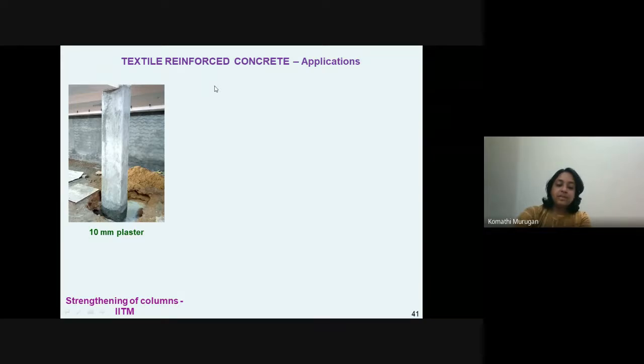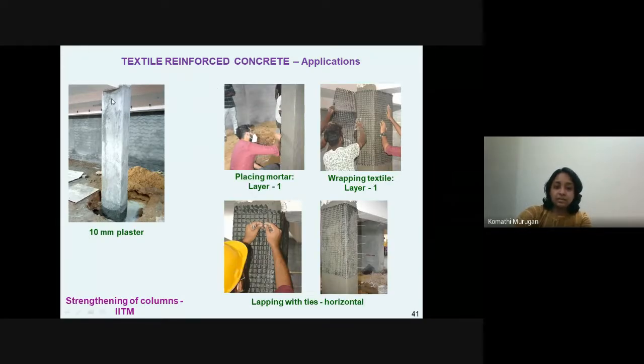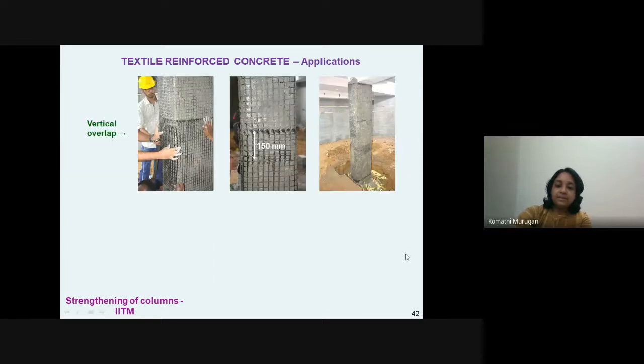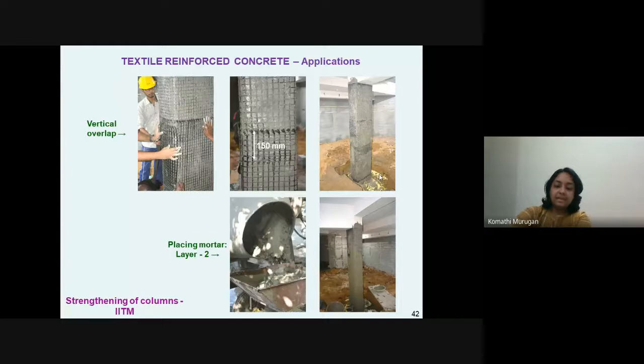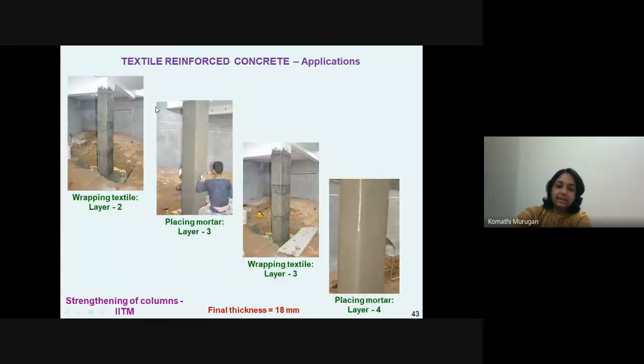What we did is we gave a plaster on the hacked surface of the columns, and we placed the mortar, and wrapped the first layer of textile, giving the vertical as well as the horizontal laps, because over the height of the column we had to give three parts of textile, as these textiles were available only at certain widths, so we had to give certain laps along the vertical directions also. And we placed the first layer of mortar, then the second layer of textile, second layer of mortar, and third layer of textile and mortar.